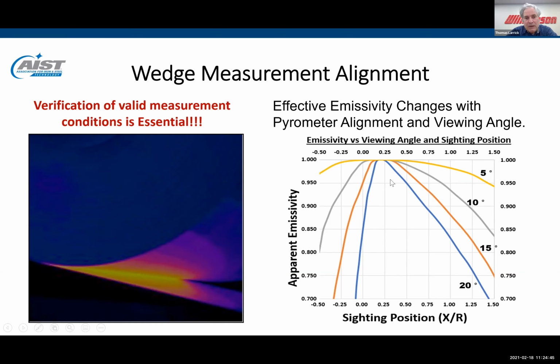in size. If you're at a 5-degree angle above parallel to the strip, your sweet spot is pretty large, but your field of view is very elongated because of the steep angle. If you're coming in at a 20-degree angle, your sweet spot is really much smaller. So ideally, you want to come in at an angle between about 7 degrees and about 15 degrees. It creates a nice, good sweet spot, but your field of view doesn't become really, really elongated.